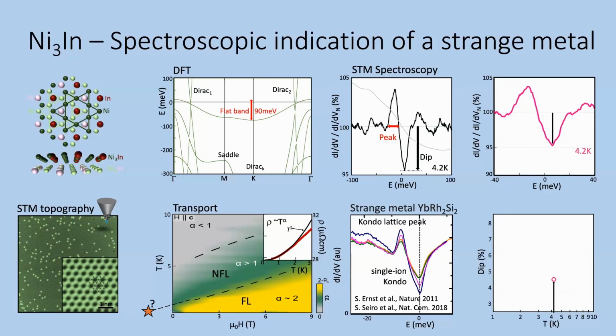So we measured the spectra at varying temperature. This is how it looks at 4.2 Kelvin. And basically, we see non-monotonic behavior. It is maximal right at the crossover temperature between the Fermi liquid and the non-Fermi liquid behavior. And in the non-Fermi liquid part, it seems to be suppressed. But at least the main message from this to us was that this peak-dip structure that we measure is sensitive, is aware of the crossover between the Fermi liquid and the non-Fermi liquid states in this material. Sorry? Zero field. This is zero field. We have also field-dependent data, and it follows the phase diagram in the right way. I don't have this. This is all at zero field.